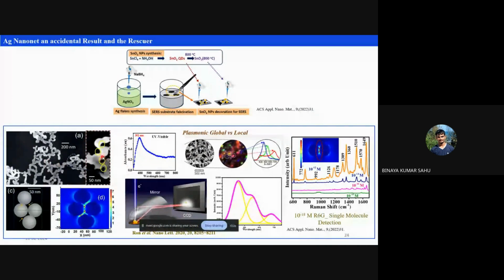And as I've shown, here the concept of the hotspot comes in. If you keep two plasmonic materials nearby, the electromagnetic confinement will be very high. This is the theoretical outcome. This technique is known as FDTD, finite difference time domain calculation. This is the actual sample, and these two are the theoretical outcomes. We did some FDTD, and we could see that if you take this kind of structure, the electromagnetic confinement is very high. And experimentally also you can see this kind of confinement.